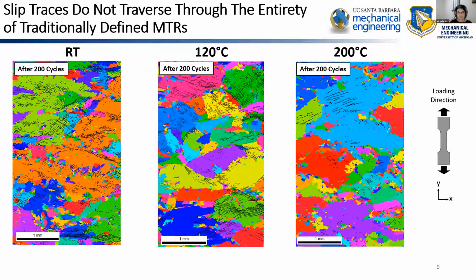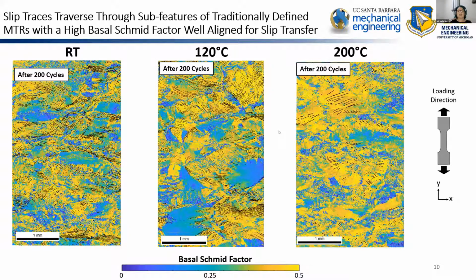And the thing that's incredibly clear from this is that those microtextured regions are not behaving homogeneously. They're not behaving as structural units or giant grains. We have slip that does exist within them, but it doesn't traverse the entire way through. These entire microtextured regions are not acting as units. And so the question is, what is this microstructural characteristic that it's behaving like, if it's not these traditionally defined MTRs? One of the things that we found is that by overlaying this with our basal Schmid factor, we see that these slip features are contained within sub-features of our MTRs that have a very high basal Schmid factor. And that can be seen to exist at every single temperature.